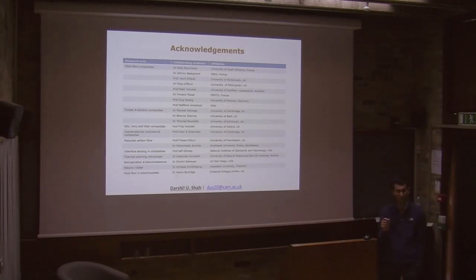Strength and weight as well, so it might be using much thicker sections. That could be a possibility. Right. But also, I'm not sure if they did longer term studies on the material, for instance, how it reacts with moisture, and sometimes they have to undergo quite rigorous testing in terms of, for instance, do the properties remain constant at temperature? So what they do in the automotive industry is stick these in at 100 degrees C for 7 days and see if the stiffness or strength has changed, but also with humidity, ranging it from 100 to 6%.